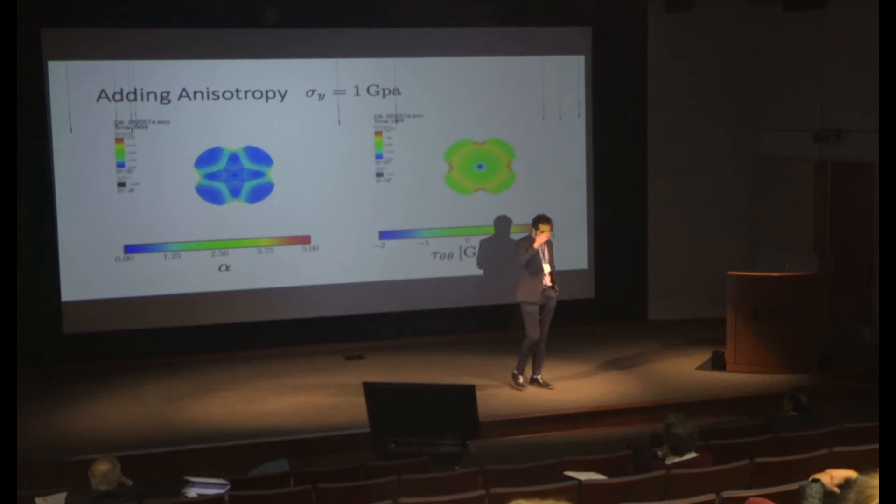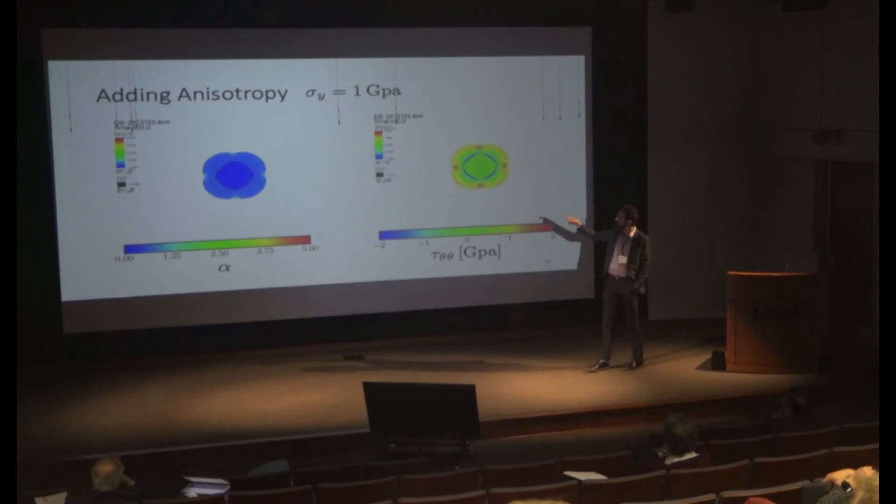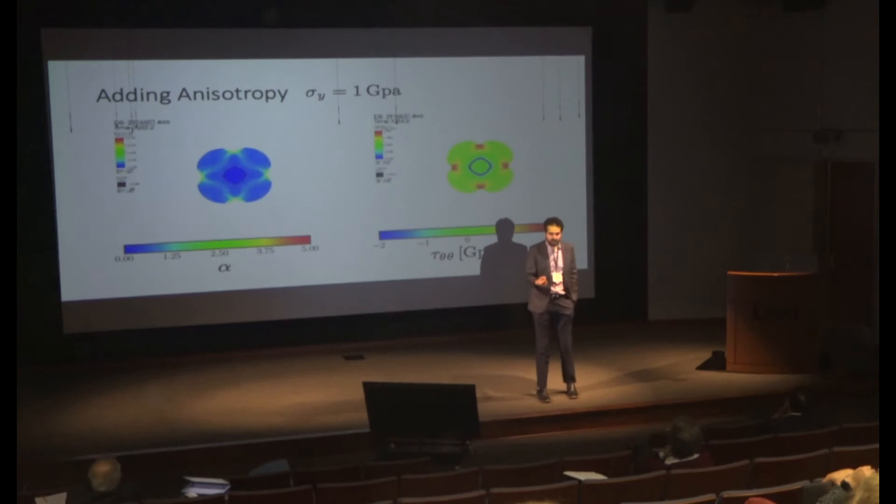This is a (001) direction silicon—I'm inserting the lithium from outside, which means I'm driving my phase change variable from outside. The thing you see pretty quickly is that when we get compressive yield and tensile yield, you start localizing plasticity. First you localize it because your core is anisotropic, so you have corners that create concentrations. But you also localize plasticity into these V-shaped forms.